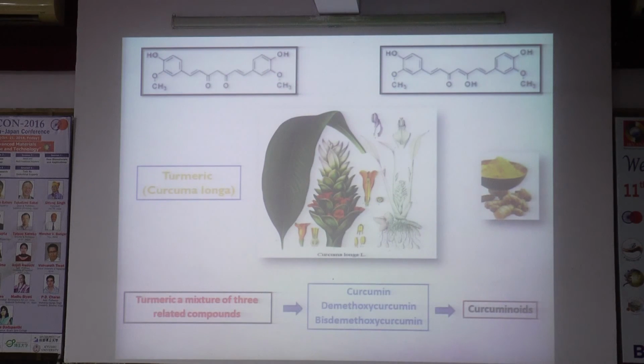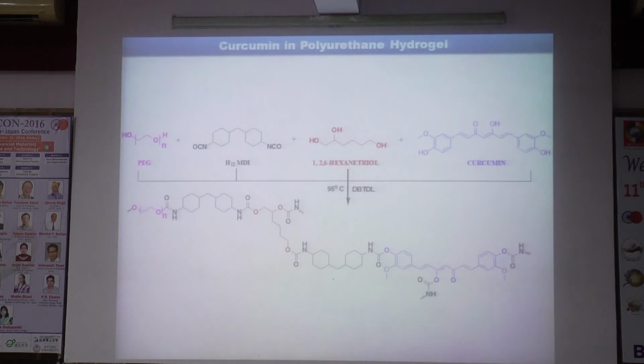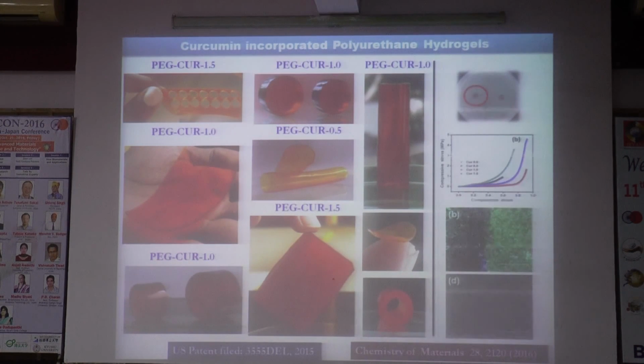So I come to the next part where we have used curcumin. You know our curcumin, haldi. Haldi is a very nice chemical and it has antibacterial properties. We are trying to use haldi in hydrogels. For example, this is the curcumin structure, and we simply use curcumin in polyethylene glycol hydrogels, and some part goes into chemical bonding, and some part is a physical interaction. So you see very nice hydrogels based on curcumin that we have prepared.